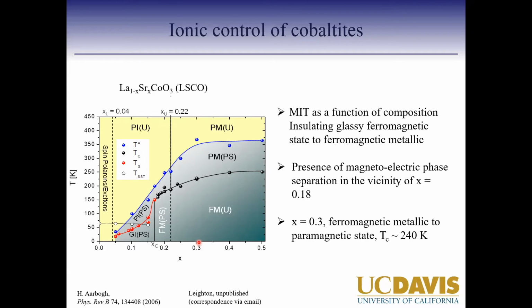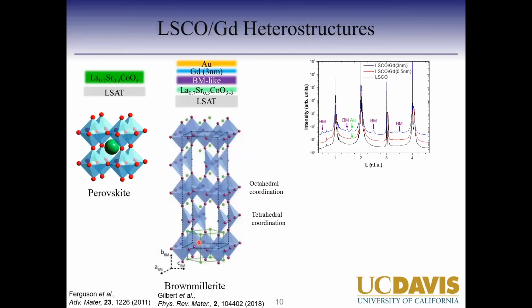So at that point, when you take the system and you start to heterostructure it with different oxygen getter layers, if you grow it on LSAT, it's a very nice perovskite crystal structure. And then if you start to add getter layers on top, like gadolinium, neodymium, or aluminum, any such material which actually likes to take oxygen and form an oxide, at that point, that heterostructure would start to change into brownmillerite. So the oxygen from the lanthanum strontium cobalt oxide would move towards gadolinium. Gadolinium would get oxidized, and you will get a signature of brownmillerite phase.